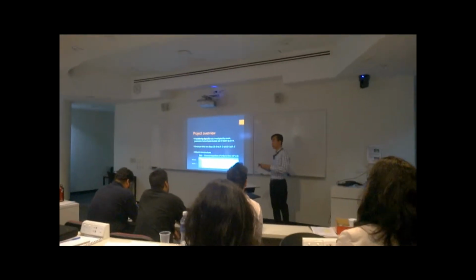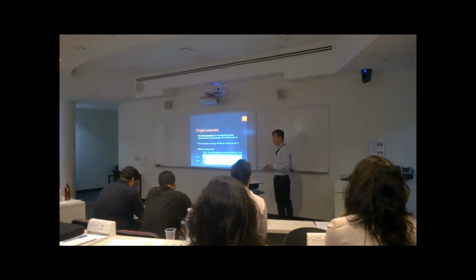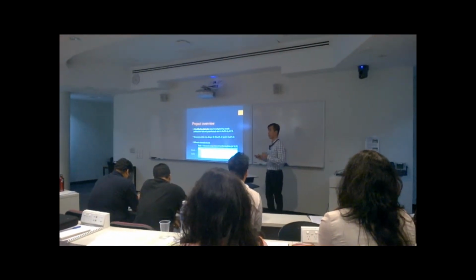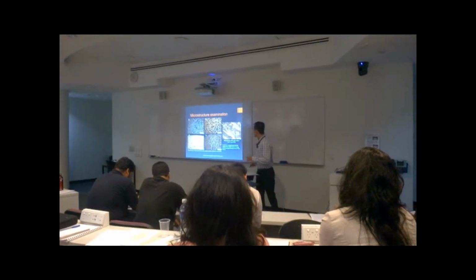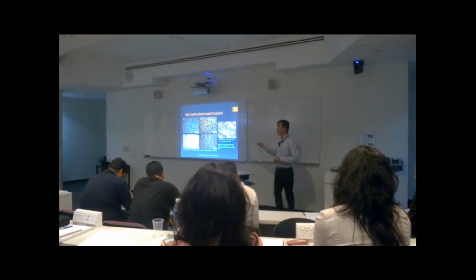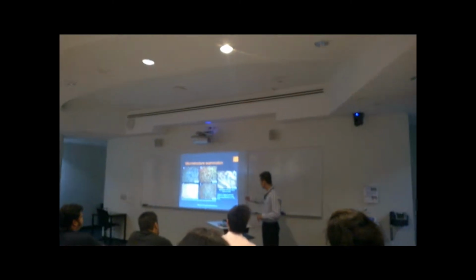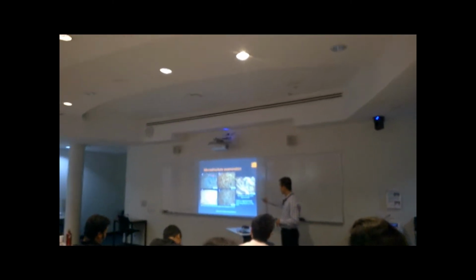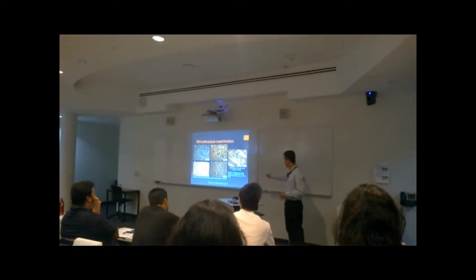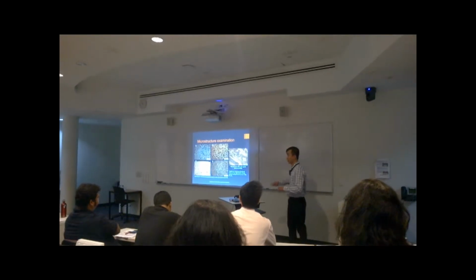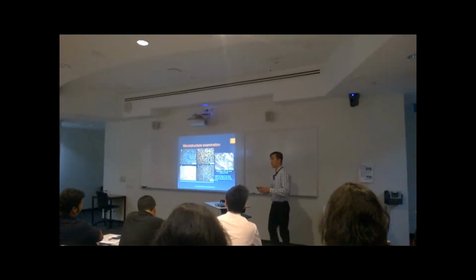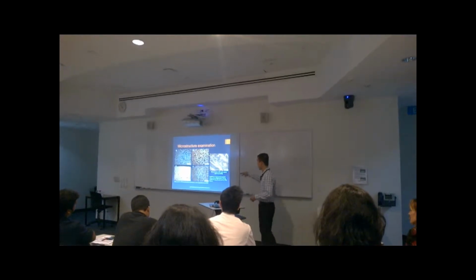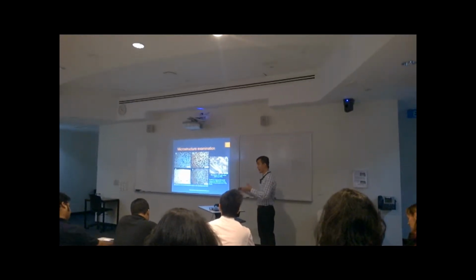So using the different microstructures and different chemical compositions, I hope I can have a very good comparison between the corrosion behavior of different alloys. So now we will have a look at the microstructures of all the alloys. As I said before, in the microstructure of hard-facing alloys, typically we got carbide, which is the white region you can see on the screen here, and the matrix is the darker region. We got a picture with a high magnification on the side here, where you can see the carbide forming and sitting on the matrix. The matrix supports and contains the carbide, so it acts like a composite material where the carbide provides the hardness for the material, and the matrix provides the toughness.